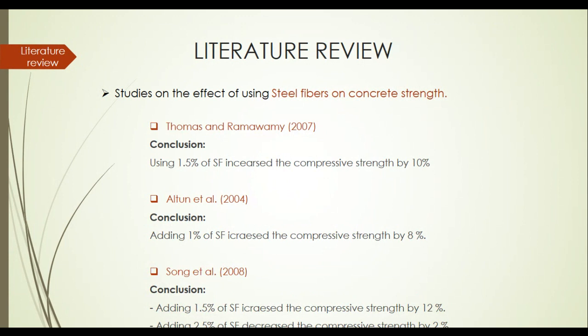While the steel fibers and concrete strength effect was studied by a couple of researchers, Thomas and Ramawamy, 2007. They concluded that a percentage of 1.5 of steel fiber increased the compressive strength by 10%, which is a good addition here. Altun et al. also found out that adding 1% of steel fiber increased the compressive strength by 8%.